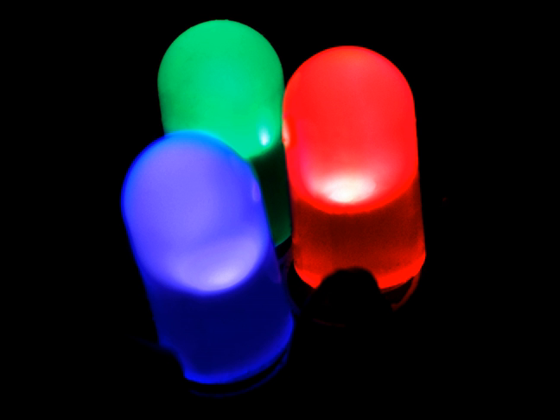White LEDs can also be made by coating near-ultraviolet (NUV) LEDs with a mixture of high-efficiency europium-based phosphors that emit red and blue, plus copper and aluminium-doped zinc sulfide (ZnS:Cu,Al) that emits green. This is a method analogous to the way fluorescent lamps work. This method is less efficient than blue LEDs with YAG:Ce phosphor, as the Stokes shift is larger, so more energy is converted to heat, but yields light with better spectral characteristics, which render color better. Due to the higher radiative output of the ultraviolet LEDs than of the blue ones, both methods offer comparable brightness. A concern is that UV light may leak from a malfunctioning light source and cause harm to human eyes or skin.